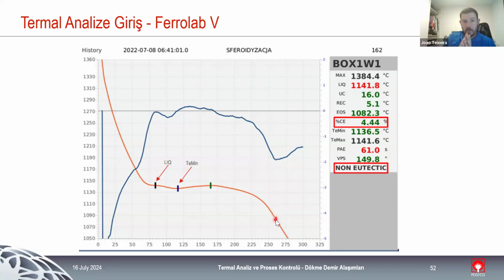Normally, if the VPS is lower, it means that most of the graphite was formed at the eutectic point, which is good for the soundness of the cast. So we don't have a lot of problems with shrinkage, micro shrinkage, and porosity. If the VPS angle is really high, and this is an example, it means that a lot of the graphite was still formed at later stages of solidification. So we can have a deficit of graphite being formed at the eutectic, and we could have some problems in the cast.